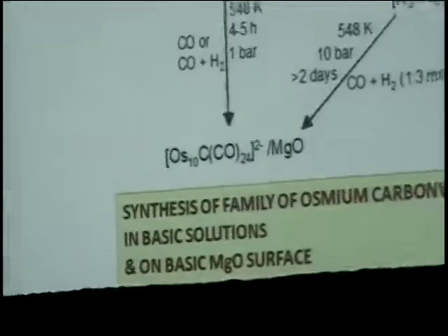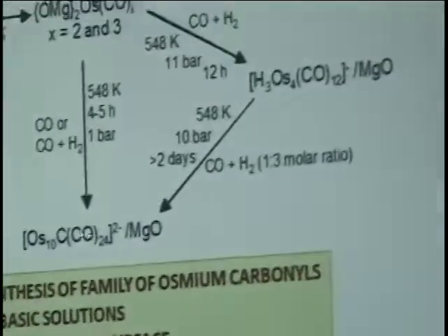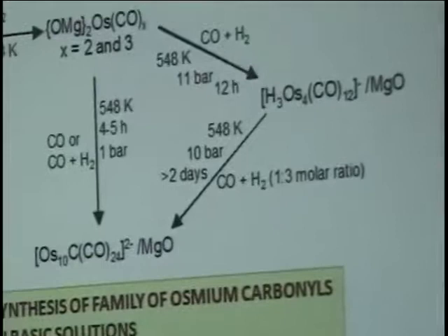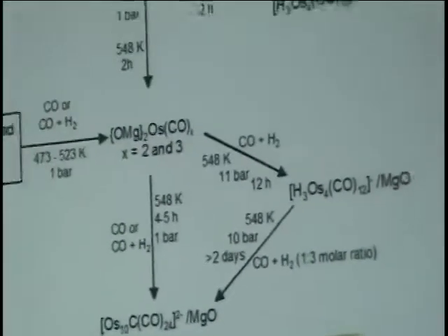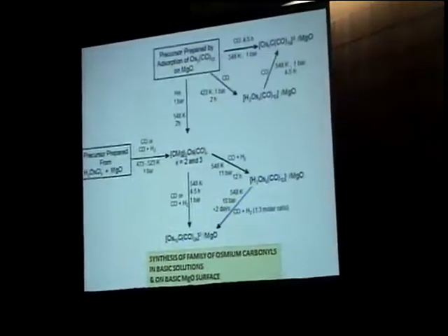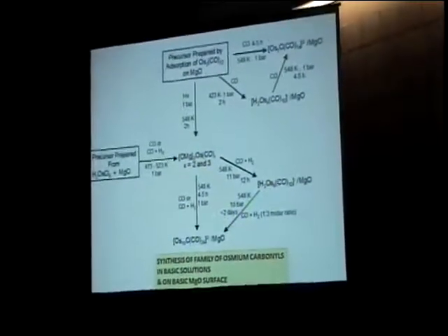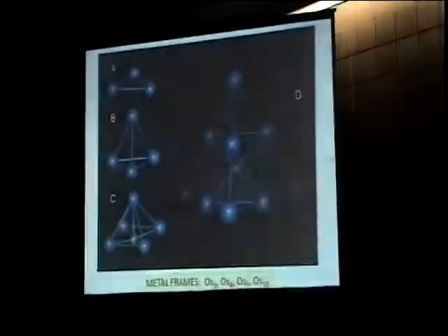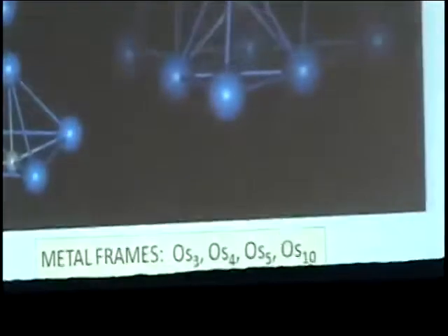One can get a 5-atom cluster. One can get the 10-atom cluster. There's a 6-atom cluster that's reported, but not yet reported on surfaces. So we can, by virtue of controlling the conditions, reactions that involve oxidative fragmentation, and really the reverse, reductive carbonylation, treat samples to get clusters of various sizes. So we're going to do more or less one at a time of these, and then we're working towards characterization of mixtures.